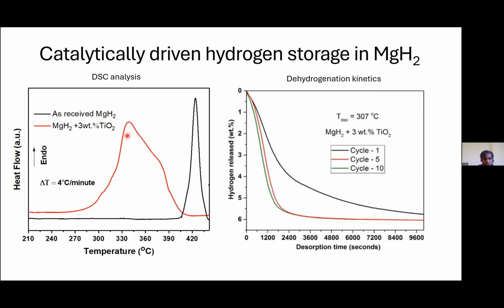All right. Once we identify this, the next question is the quantification of hydrogen. How much quantity of hydrogen does it provide? So look, this is a temperature closer to 300 to 350, say. At this temperature, I can operate this system. So I choose an appropriate temperature under isothermal condition, that means constant temperature. Now I would evaluate how much quantity of hydrogen is released. The black one is the first cycle. It means the as-prepared material. Well, very good. It's really good. That provides a capacity closer to 6%.